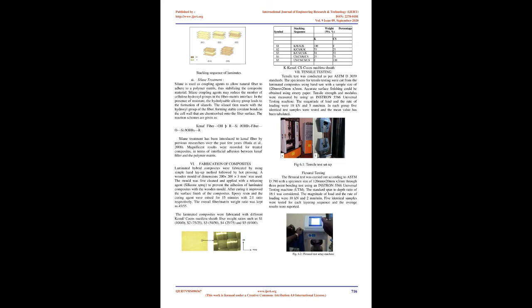The Cocos Nucifera Sheath is an agrowaste which is available everywhere. The Cocos Nucifera Sheaths were collected manually from Seri Kembangan, Malaysia. The Cocos Nucifera Sheath wastes were collected manually from the coconut tree. The sheets were immersed in the water for 1 week and then they were thoroughly washed with both tap water and distilled water. After complete removal of debris, the sheets were dried in the hot sun for 1 week. Finally, the sheets were cut into the required size for fabrication.